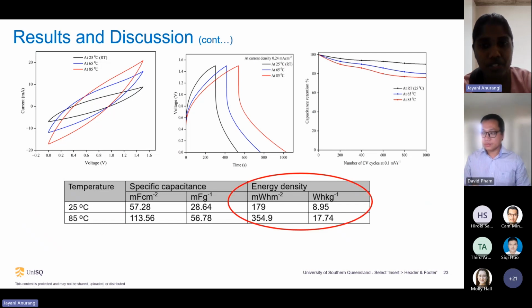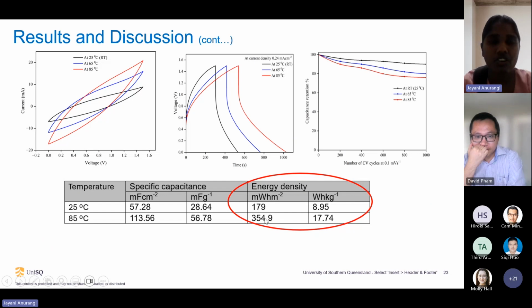For my final sandwich composite panel, I evaluate the energy density with respect to the area and with respect to the weight. According to this value, you can see the final sandwich composite energy density with respect to the area is 179 milliwatt hour per square meter and 8.95 watt hour per kilogram. That is the energy density of the final developed composite panel. In addition to these two tests, as earlier, I evaluate the durability of the sandwich composite at 3 different temperatures. According to this test, it was noticed that at each temperature, the developed panel has more than 75% capacitance retention.